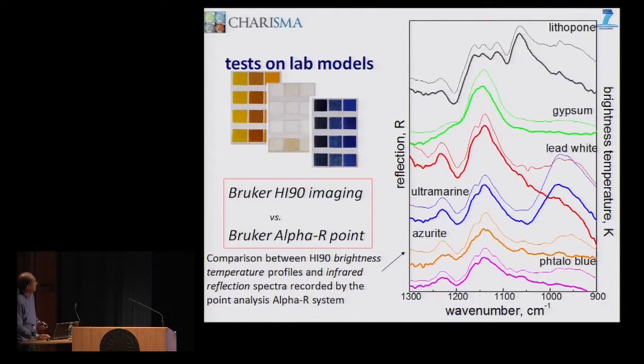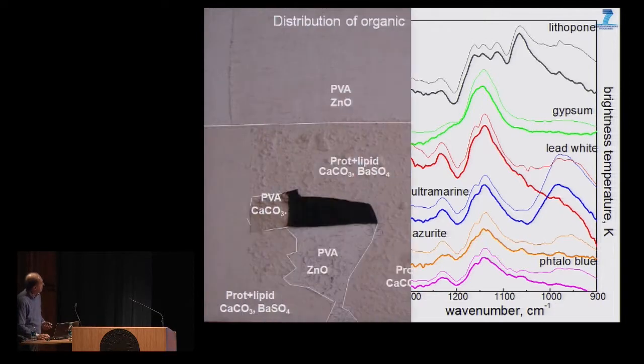And we carried out measurements exploiting the fact that the response of each pixel in the detector is very good in terms of spectra with respect to the Bruker Alpha, that is, maybe you know, a portable infrared spectrometer that is not expensive but is very diffused in the various laboratories. And you can see that the spectra obtained by each different pixel of the HI90 and the one of Bruker are very similar.